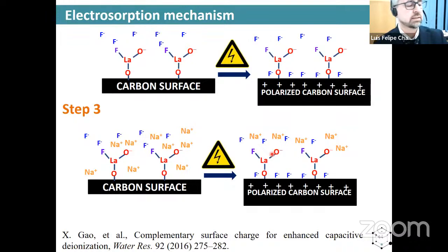So then this mechanism agrees well with the Donnan amphoteric model. This model was very useful to describe these results because it says that a positive surface is better suited for anion electroadsorption due to a decrease in the energy needed to modify the surface excess. I mean, so you have less co-ion expulsion, or a higher electrode charging.